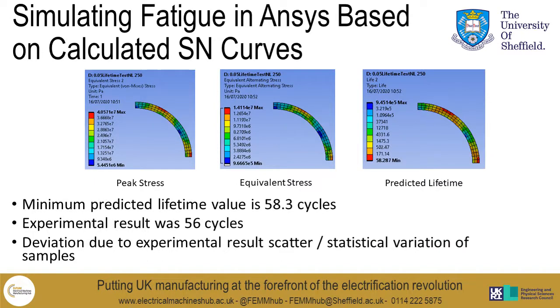It's possible to take the lifetime data predicted in the previous slide and input it into ANSYS to allow different cycling conditions to have their lifetimes predicted. By way of example here, we've recreated one of the samples from the test subject. You can see, shown from left to right, we can calculate the peak stress due to its temperature. We can then also calculate its equivalent stress, which is due to the temperature excursion. And finally, we can use that value to determine the predicted lifetime.